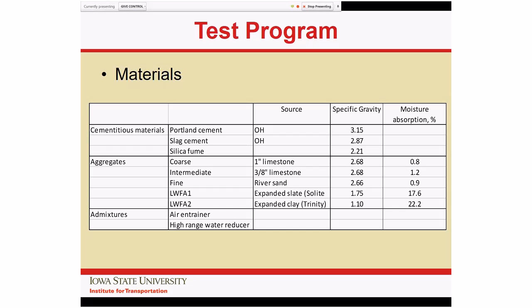We also obtained samples of 2 lightweight fine aggregates from 2 different manufacturers, again from Ohio. So we were using the critical materials that are available in your area. Admixtures, we obtained locally available chemical admixtures as air entrainers and high-range water reducers. We measured the specific gravities of all of the materials, and you'll see that the lightweight materials are considerably lighter than the conventional materials and also have considerably higher moisture absorption. And that's exactly what we want. I think the specification that we've published recently, we're asking for absorptions greater than 15%.